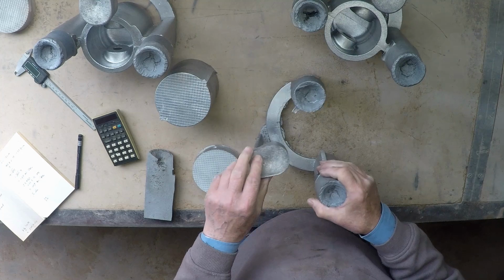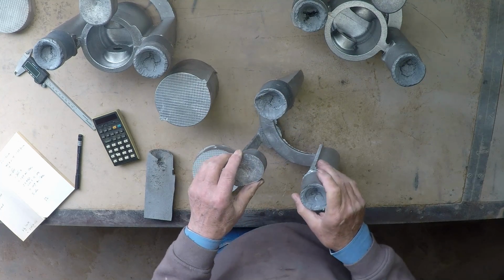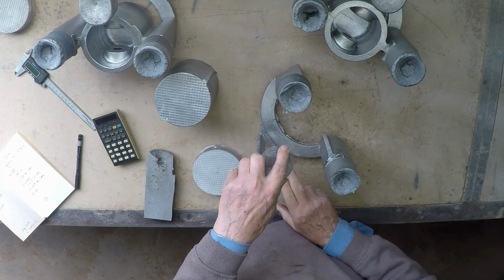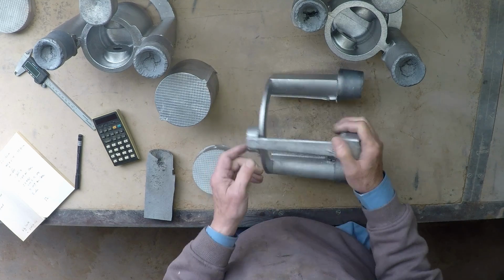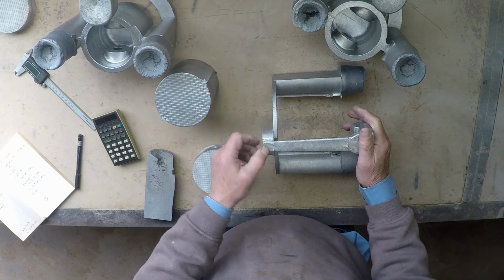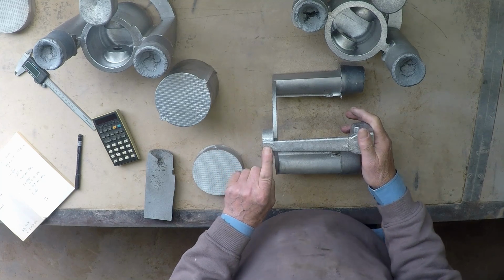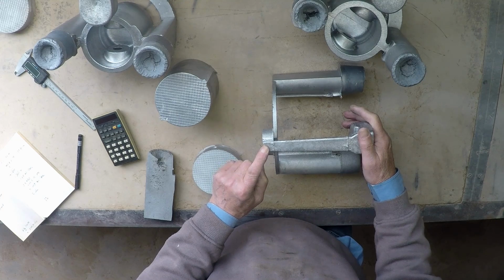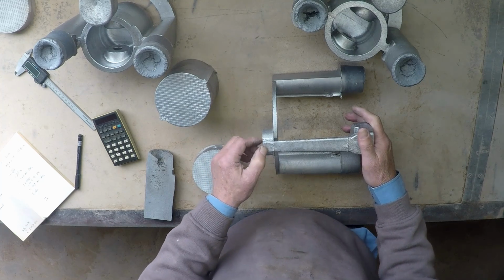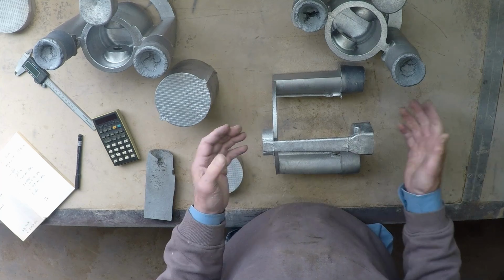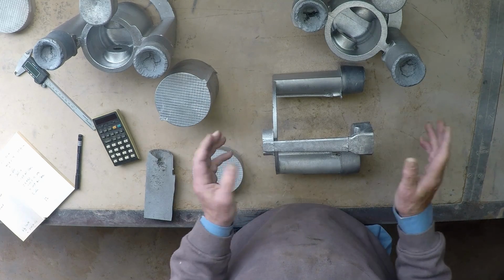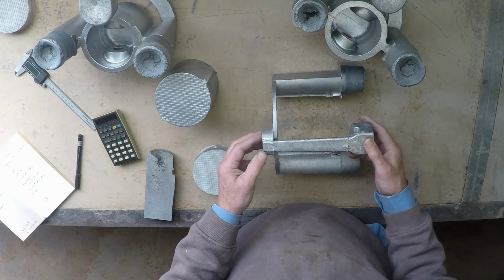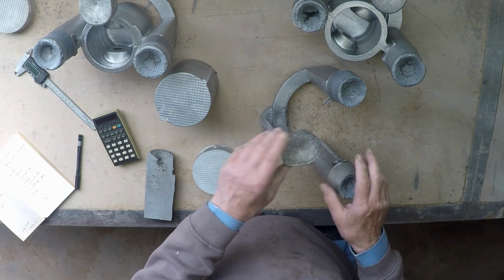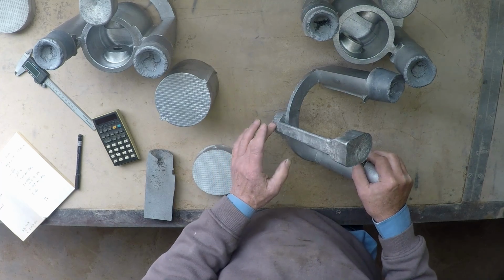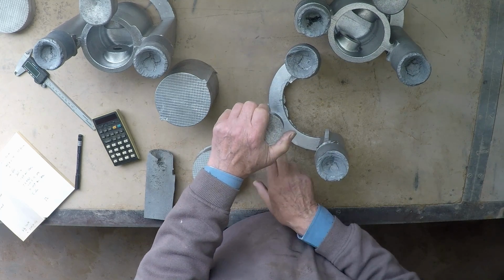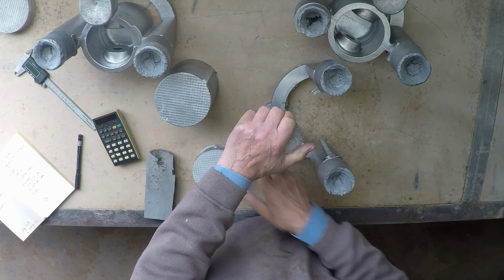The filter, as I said before, it's not really to clean the metal. It does a bit of that, sure, but its main purpose is to slow the metal down. At the bottom of this sprue, the metal will be doing pretty close to 2 meters a second. Now, you really shouldn't pour metal into a mould any faster than about 0.5 meter a second, but it's very hard to get down that low. I mean, you can get away with about 1 meter a second, but really the 0.5 meter's desired. So what the filter will do is slow that 2 meters a second down by a factor of 4 or 5 to hopefully 0.5 meter a second.